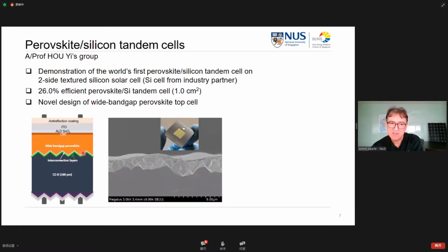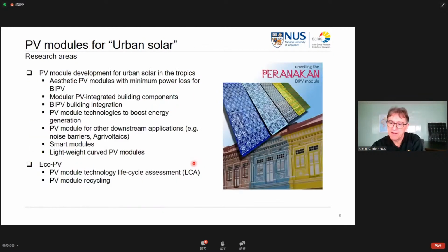But for blue light or green light, the conversion efficiency for silicon is not so good. For that, we can, for example, try perovskite, a wide bandgap perovskite material, and we learn to process that on the silicon cell, which is actually textured to minimize reflection. We have a strong team, more than 30 people working on this, and our efficiency is at 26% at the moment. You see that they are using 1 square centimeter device area, and I think we are world leaders with putting perovskite on silicon textured on both sides, which is industry standard actually in the